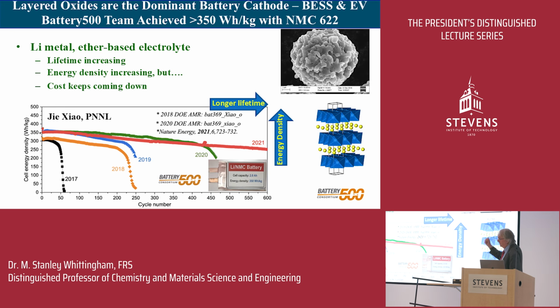We are using pure lithium metal, not the safest thing. We're going back to the old Exxon electrolytes, the ether-based electrolytes, because they plate out lithium better. So everything's gone full circle. So this is the typical layered structure. So what's happening today is everything's moving forward, the energy density is going up, the costs are clearly coming down, and we'll get back into that later in the talk.